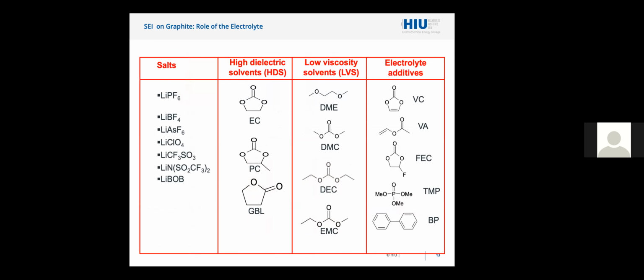Talking about salts, at the very end, there have been many salts which have been investigated. My first lithium-ion battery I made about 30 years ago for a rechargeable hearing aid used LiAsF6, which is an exceptionally good salt, but unfortunately it's too toxic. Lithium perchlorate is, for example, explosive when it's very dry, so it's very difficult to use. And most of the proposed salts so far have some problems. They are either not conductive or toxic or explosive or corrosive and so on. So at the very end, the salt of choice is LiPF6.